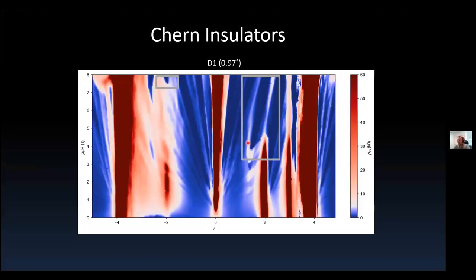So this is now one of these Landau fan diagrams that I showed you before, but I showed you only up to 4 Tesla. Now, if you go to 8 Tesla, you can be a little bit away from the magic angle, and again you see the same physics. I'm highlighting here this state that emerges basically out of nowhere at finite field, and you can have the same state for a whole side. It requires a little bit higher field to see, and this is just a color-coded Rxx.